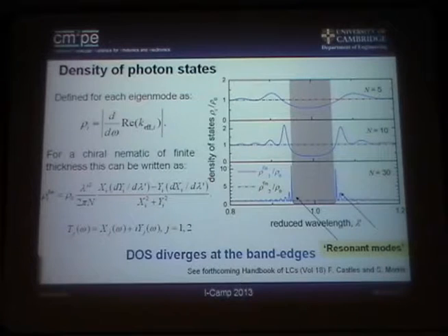And from the point of view of lasing, the interesting point here is that there are only two well-defined modes. So unlike a Fabry-Perot cavity, where you've got lots of modes and have to engineer another way of selecting that mode, the structure itself only has two very well-defined discrete modes. There are potentially other higher-order modes, where the density of photon states decreases as you move further away from the edges, but the difference in gain between these two regions is very large, and so all you will see is that these two are the dominant modes. And then there's an additional criterion in selection in terms of isolating just one of these modes. So it's these two. These are the band edge modes corresponding to the density of photon states, and that's easy to simulate.